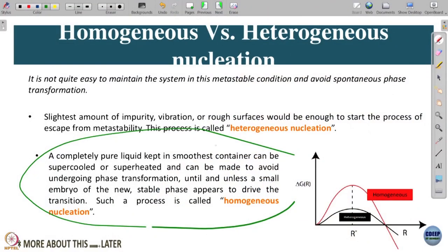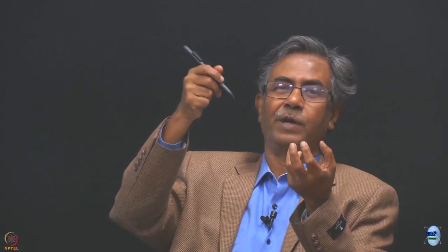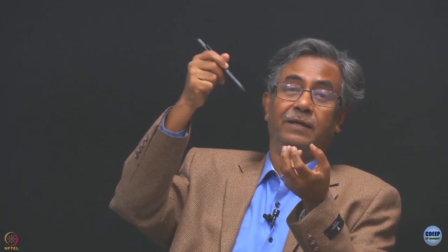So, this is a completely smooth way, and one interesting thing is that you might have done in physical chemistry experiments that you have supercooled a liquid in a container below 0 degree centigrade. Now, you scratch it, and many of us have seen that. Or any liquid, you scratch it with a glass rod, and you can see crystallites appearing. So, that is heterogeneous nucleation, and this is one of the telling and great examples of the role